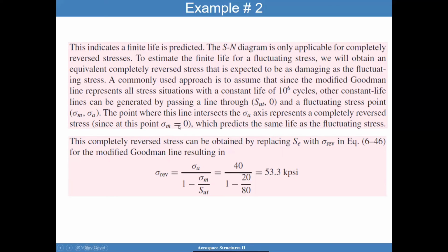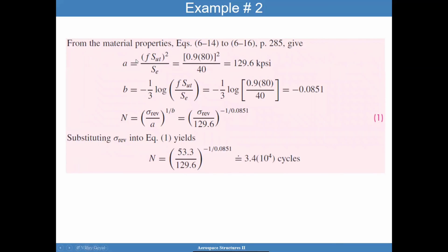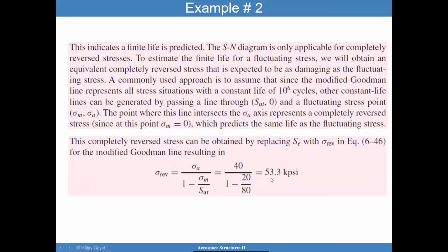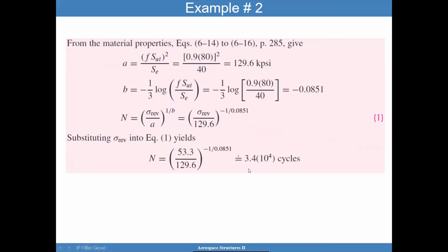And that equivalent value is sigma m equals 0. So you can use that to figure out what that is. And that point is going to be 53.3, okay? When you figure out where it intersects. So since it's 53, we're going to use that later. The first step is to find A and B. So F is 0.9, SUT is 80, endurance is 40, calculate A, calculate B. Again, this stuff without the 2, log 1/3. And then you have this value is 53 from this equation. And so from there, the number of cycles gives us 34,000 cycles. And so you get 3.4 10 to the 4th cycle. Sorry about that.